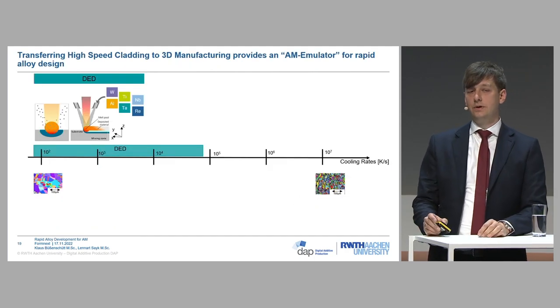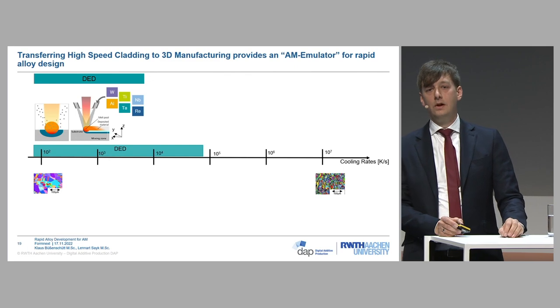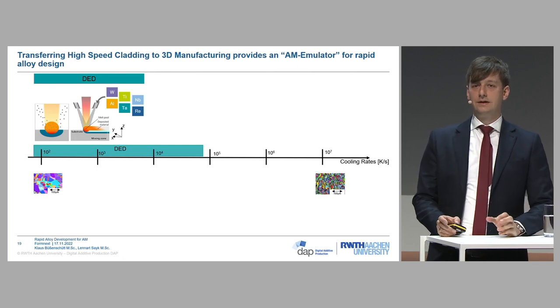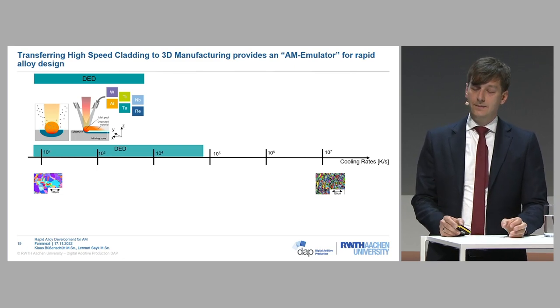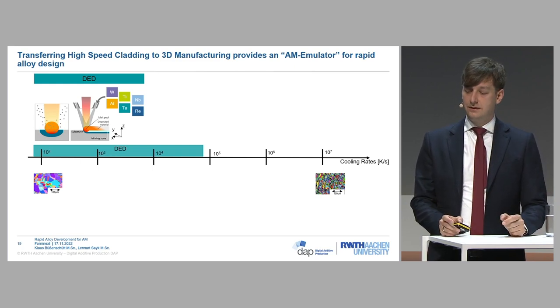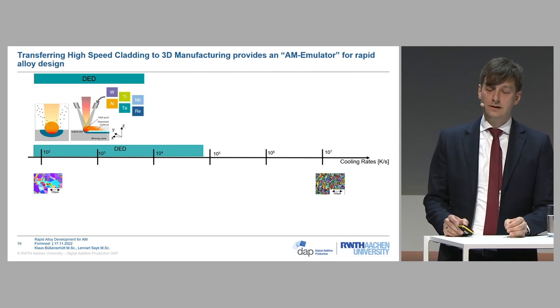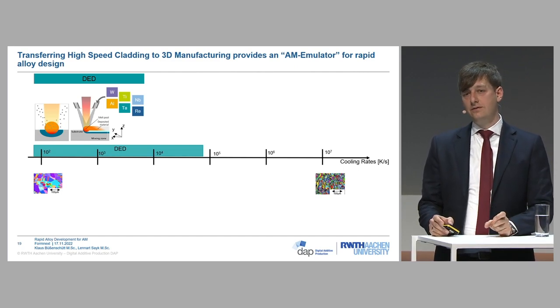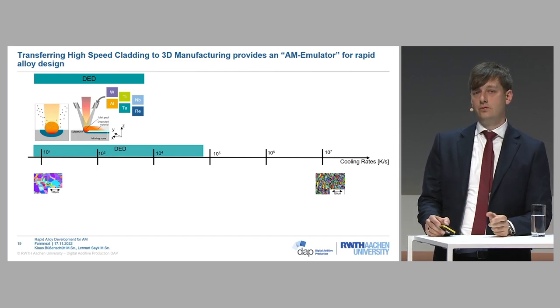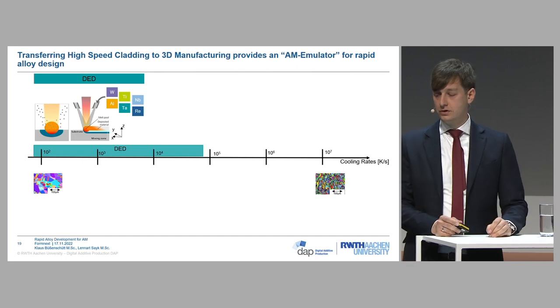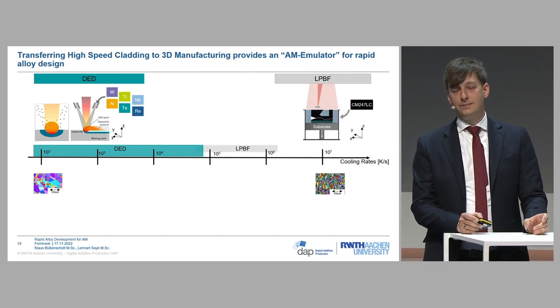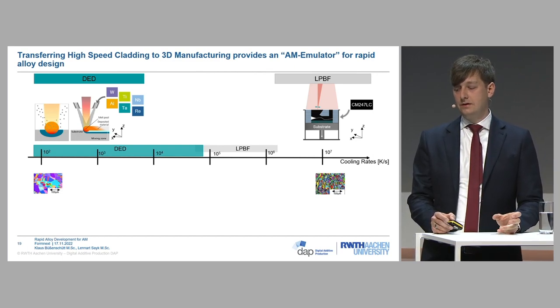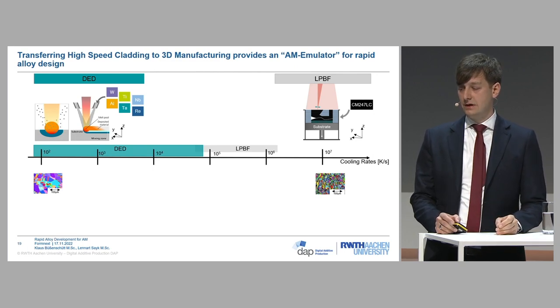The second challenge is that this process was developed for conventional DED and cannot be directly transferred to laser powder bed fusion. DED is characterized by certain cooling rates, and the cooling rate has a high impact on the produced microstructure. Unfortunately, the cooling rates of laser powder bed fusion do not overlap with those of DED processes, meaning using just DED as an AM emulator is not feasible.